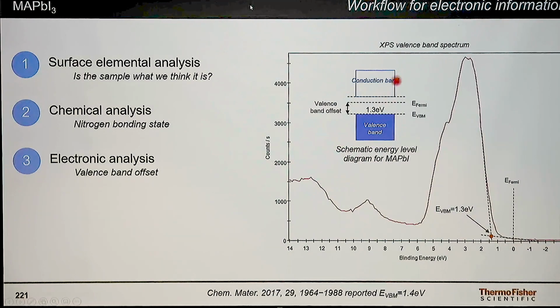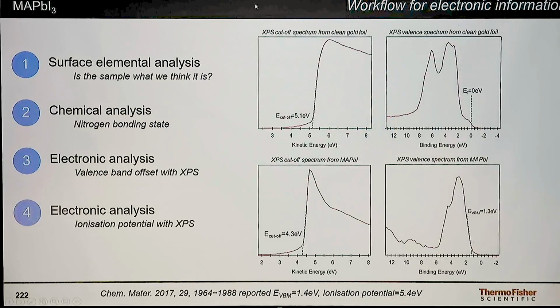Then we can use, and in this case we're looking at the valence band using XPS rather than UPS, but we're doing exactly the same thing as we saw in the UPS data earlier on with the PFO sample. We're just measuring the valence band offset, so the onset of photoemission, and determining where that is to measure the ionization potential ultimately. So using that, and we have our measurement of the cutoff at one end, we can measure not the work function, in this case the ionization potential, and use that to calculate the value using these two values, knowing the Fermi level, so this is on gold, to get the work function here. Then using the position of the Fermi level, our highest occupied state, and the cutoff, we can then measure the ionization potential of 5.4 eV.